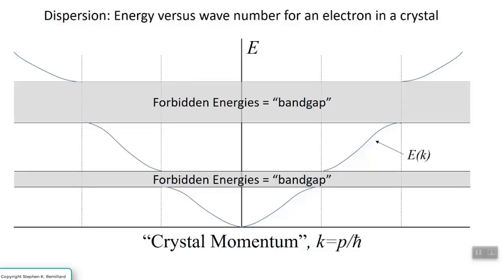An electron can have any energy except for the energies in these grey regions, but an electron can have any momentum, any wave number can belong to an electron, but at a certain wave number it is going to make a jump. And this is referred to as the Brillouin zone edge, or these vertical dashed lines. This is a consequence of the periodicity of the potential energy.